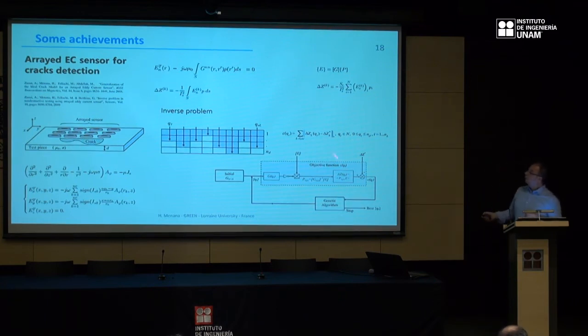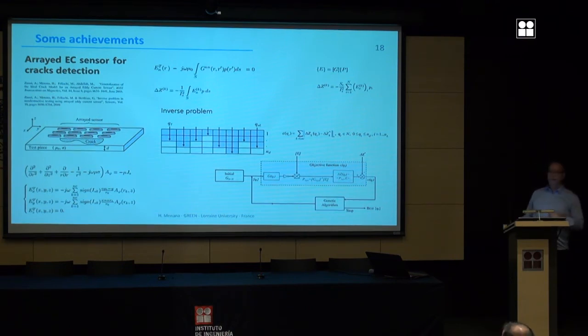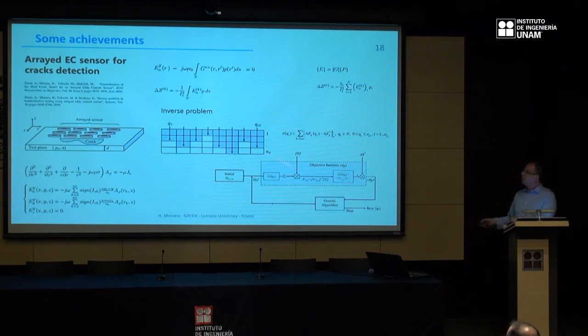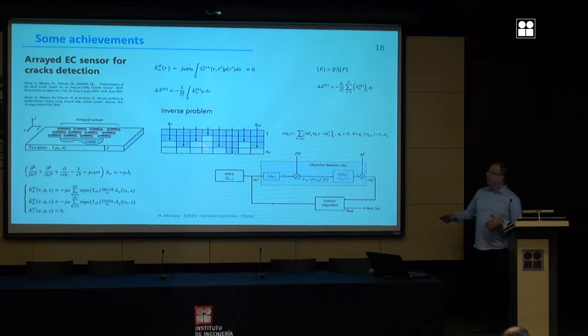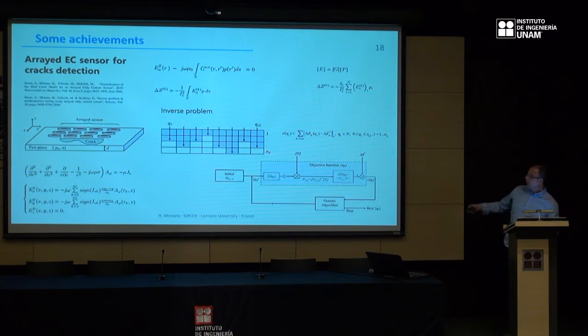So it's a singularity. The crack is supposed to have no thickness. For the inversion, we considered the crack as an array. Instead of looking at the exact shape of the crack, we represent it in a discrete form like this, by an array. The number of elements of the array is a discretization in this direction, and the value of each element of the array is a discretization in the other direction. We used a genetic algorithm to reconstitute the shape of the crack based on the measurement of the impedance variation in each coil here. I can explain more if you want after.